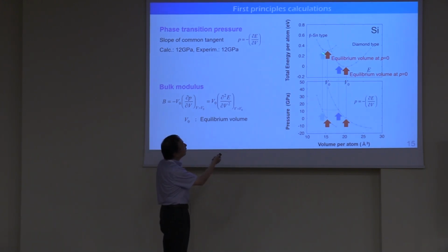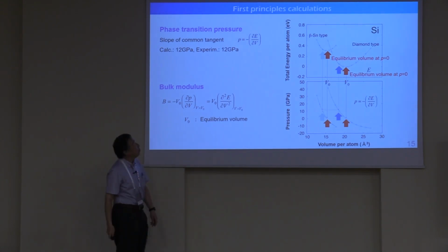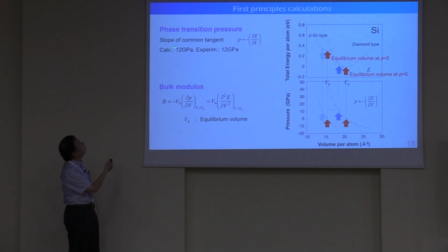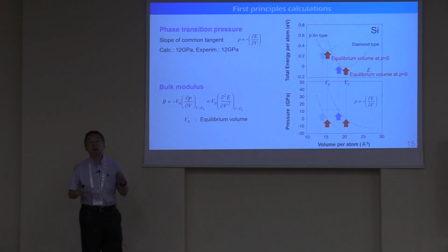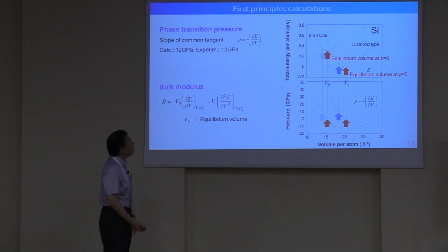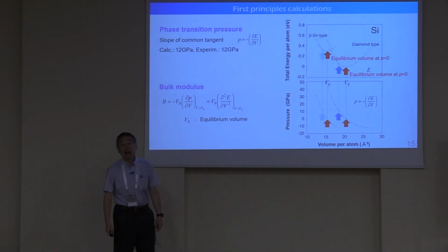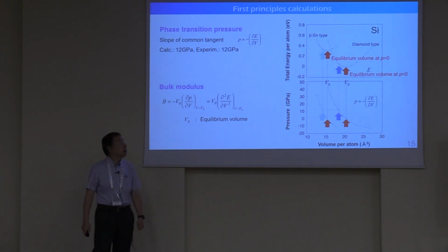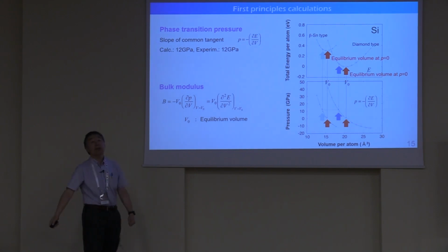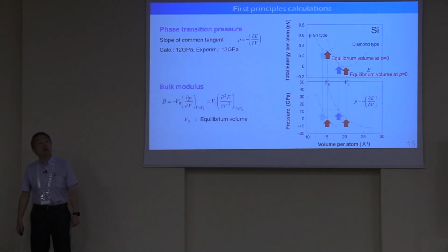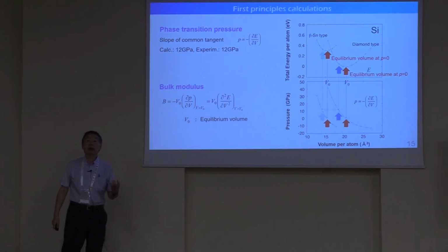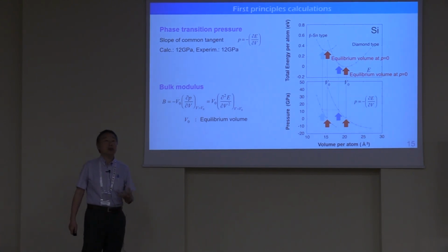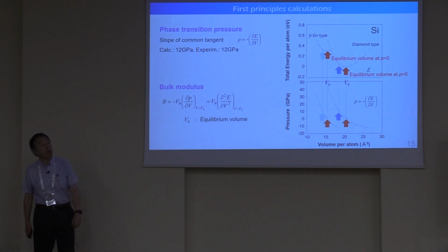And if you make the common tangent of these two curves, the slope of common tangent corresponds to the phase transformation pressure. Because at this pressure, the enthalpy becomes the same between these two phases. So it corresponds to 12 GPa by theoretical calculation. And it is the same by the first principles calculation. So first principles calculation can accurately predict at which pressure the phase transformation takes place. And it is in good agreement with the experiment.